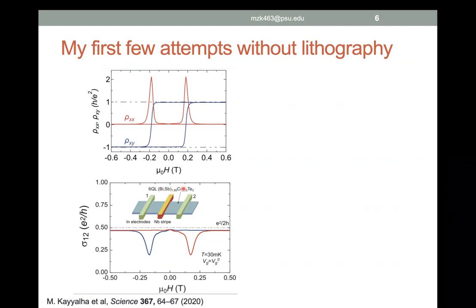And then I did a bunch of sanity checks. So first I looked at the Hall and longitudinal resistance of this sample. I saw that the Hall resistance was quantized, longitudinal resistance was vanishing. So I concluded that, okay, I have a relatively good quantum anomalous Hall sample. Then I deposited a niobium strip on top of these samples.